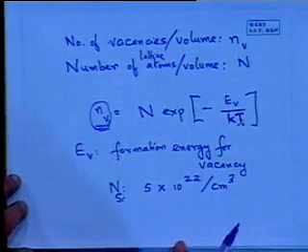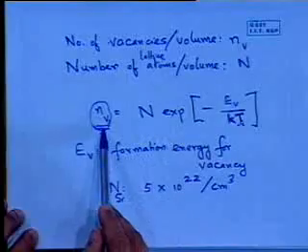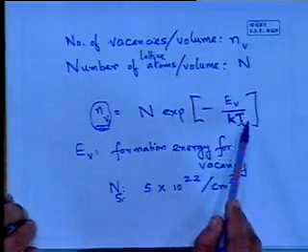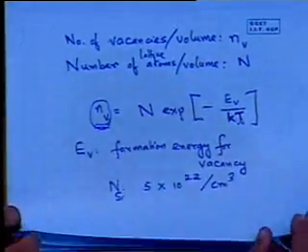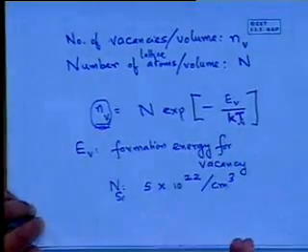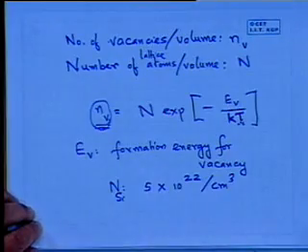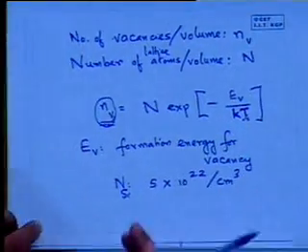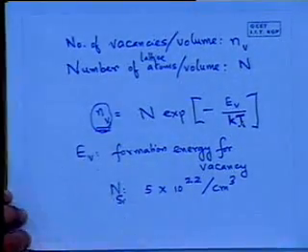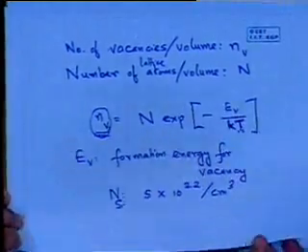And that's what we do in practice. We experimentally try to determine various processes like this, whether it be vacancy concentration or other things described by the Arrhenius equation, as a function of temperature, and we extract the activation energy. When we know the activation energy for a certain process, we can comment on possible mechanisms for that process. So if it's an unknown process, I see the activation energy calculated, and then I say, oh, it may be related to this behavior or that behavior. This is a very important technique that allows us to understand what is really happening in that material.